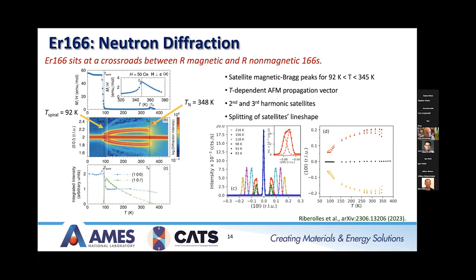As you cool down through TN, you start seeing these incommensurate Bragg peaks appear, and the position of these satellite Bragg peaks is temperature dependent. So the antiferromagnetic propagation vector that they correspond to is temperature dependent, and it seems to grow and then decrease as you go towards the T-spiral transition.